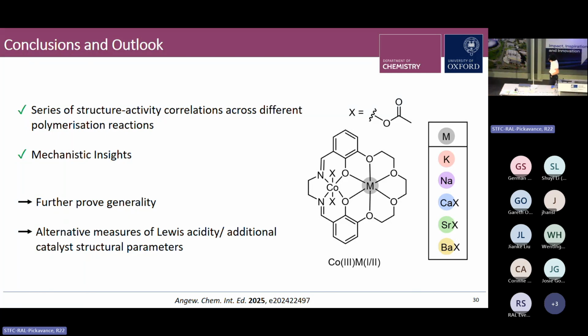So we have tried to plot binding constants of the S block metal in a 18 crown 6 model versus catalytic activity, and they don't correlate. We haven't measured the binding in our specific catalyst system. However, we have looked at changing the crown ether size, for example, making it smaller for like a 15 crown 5 unit that you think sodium would be better suited for, but it doesn't improve the catalytic activity versus this 18 crown 6. For the same metal? Sodium. Yeah. The sodium in 18 crown 6 versus sodium in 15 crown 5 does not improve. It actually worsens catalytic activity and makes the complex very hard to make. We had this exact same thought, and it's a really interesting point, but we think perhaps binding affinity is not the key parameter.